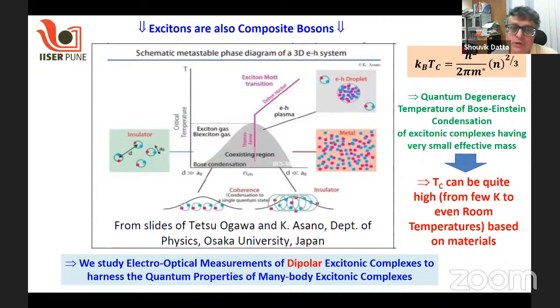Another very important aspect of excitons is that they are composite bosons. Overall, they have an integer spin. And the quantum degeneracy temperature for Bose-Einstein condensation of bosons is inversely proportional to the effective mass of these bosons. Excitons being just an electron-hole pair, the effective mass can be very, very small compared to, say, the rubidium atom, which atomic and molecular physicists actually study. So, based on materials, the transition temperature for observing Bose-Einstein condensation of excitons can be quite high, from a few Kelvin to even room temperature, depending on what kind of material and structure you are dealing with. Our experimental investigation will focus mostly on electro-optical measurements of dipolar excitonic complexes to harness this quantum property of many-body excitonic physics.